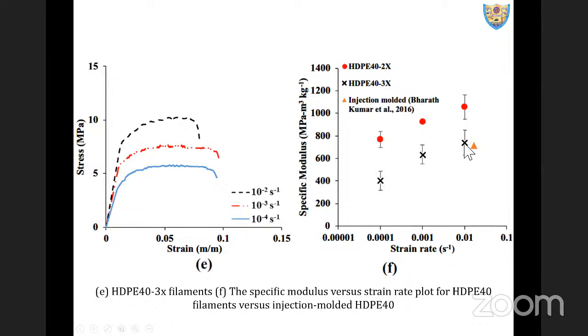And what did we see is 3-time extruded is performing better than the 1-time virgin injection molded sample. So this means it definitely makes sense to utilize this filament for 3D printing, wherein the 3D printed part is going to perform superior to the injection molded sample. So this probably is a good counter check that all of us can do whenever we have developmental efforts. And here the same filament has been tested for 3 different strain rates. ASTM standard says 1 strain rate, but you can always increase or decrease the strain rate, which will give you additional insight into material behavior.